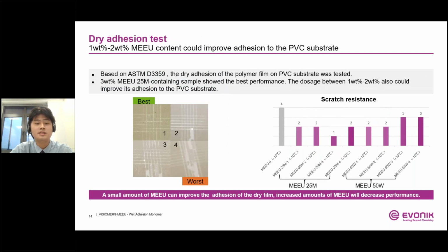And next, let's focus on the dry adhesion test. These samples were tested according to the American standard ASTM D3359 coating scratch resistance method, and the emulsions were coated on PVC board, which is a kind of polar plastic, using a multi-blade cutting knife to line and tear with a standard tape. Scratch resistance is judged according to the state of the grid lines, as shown in the image on the left side. A higher number means more film peeling off and worse performance.